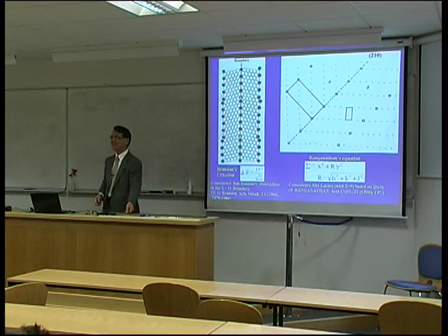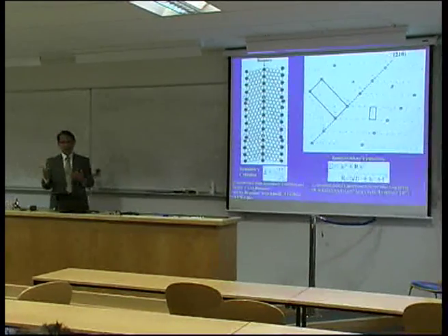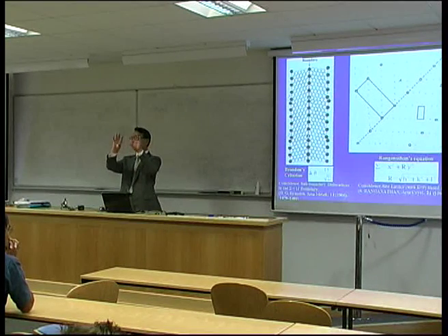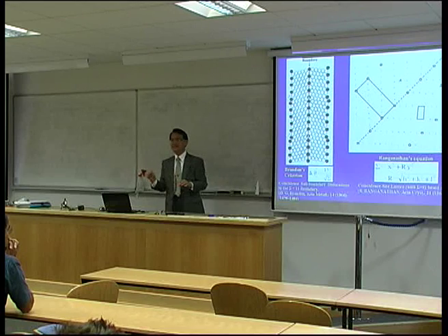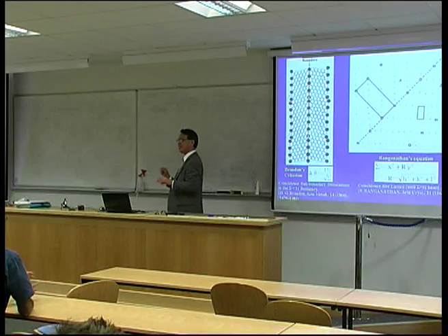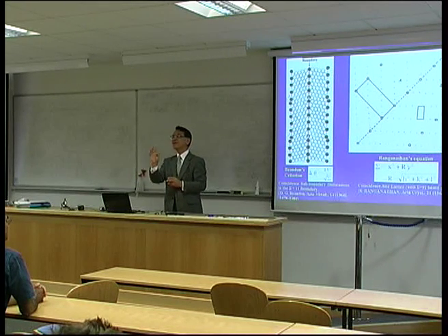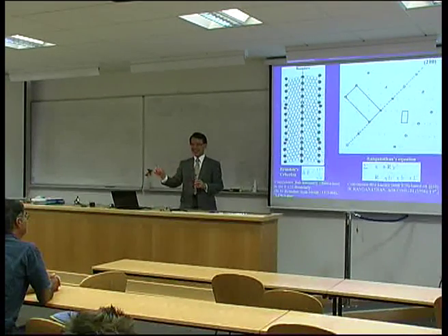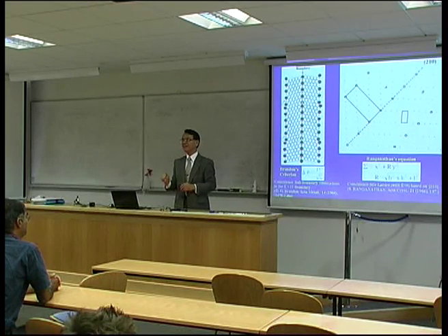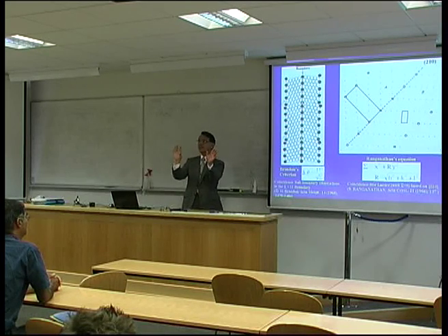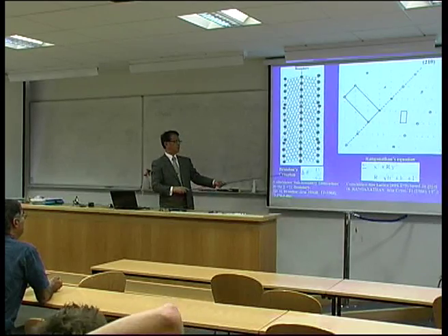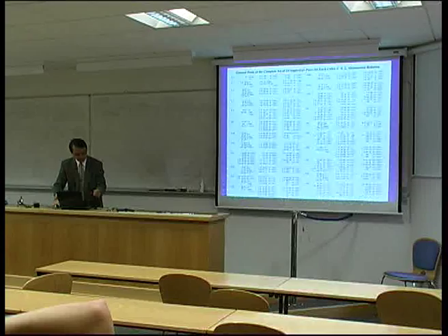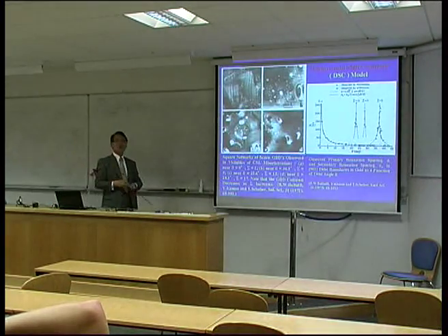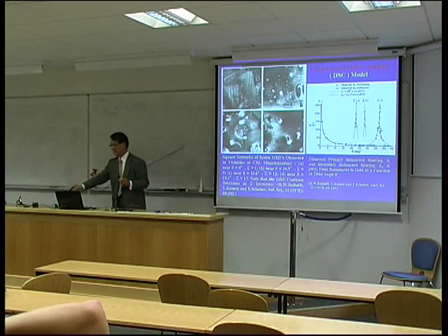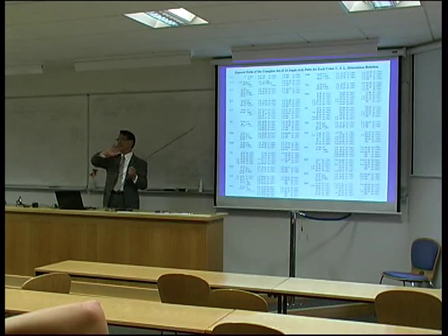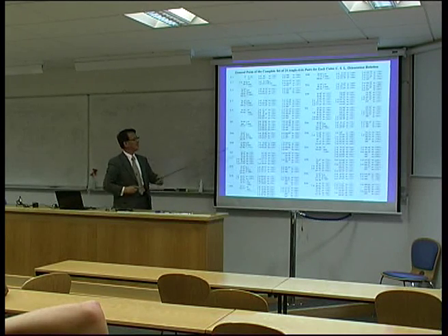So nowadays, as I'm going to show, we can characterize individual grain boundaries in real polycrystalline material by using a very advanced microscope, the orientation imaging microscope. The instrument is the same, so the fully computerized machine automatically characterizes the individual boundaries. But in that case, of course, it is not exactly coincidence, or there is some deviation but allowed depending on these criteria. So remember this. In the orientation imaging microscope, such a table is already taken into the calculation. This is a background. So you have to remember.